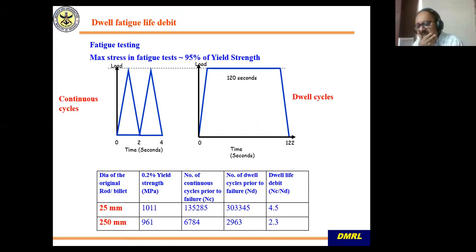Then I come on to another important property, which is known as dwell fatigue. Most aero engines experience this. As compared to a sawtooth kind of wave, what we do in dwell fatigue is hold the load at the highest point for some amount of time, and that causes a decrease in fatigue life. This is known as cold dwell fatigue, because it happens at lower temperature, and this is very pronounced in near alpha alloys and alpha plus beta alloys.